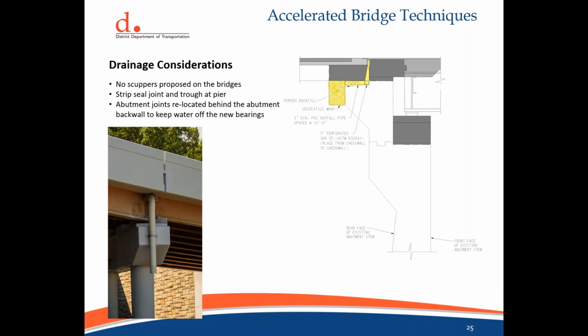Now I'll discuss some of the drainage considerations that we encountered on this project. The existing bridge had scuppers near the abutments, and the downspouts were actually cast through the abutment concrete and drained near the top of the footing. We ended up eliminating the scuppers on this bridge. Due to the inability to use a continuous beam due to the loading on the substructure, we ended up using, as John mentioned, another open joint at the pier, similar to the as-built condition.